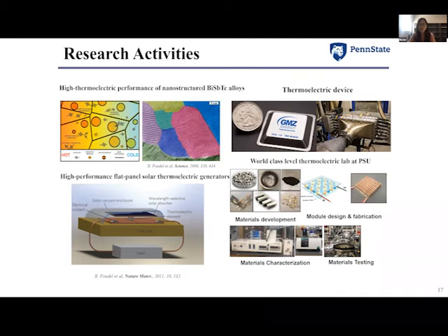convert the solar radiation into heat and thermally concentrate it onto the thermoelectric element, creating a very large temperature difference across the thermoelectric device. At the end, a 7 to 8 times higher conversion efficiency compared to previously reported. The best value for a flat panel solar thermoelectric generator is achieved, resulting from this innovative design that exploits the high thermal concentration in an evacuated environment.